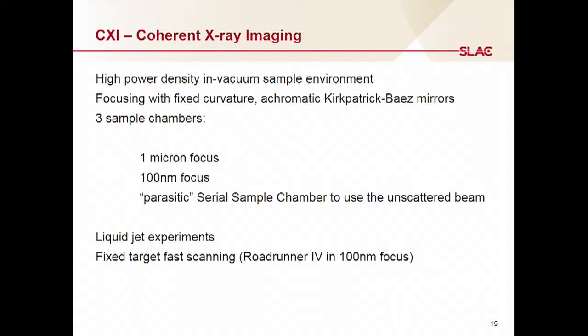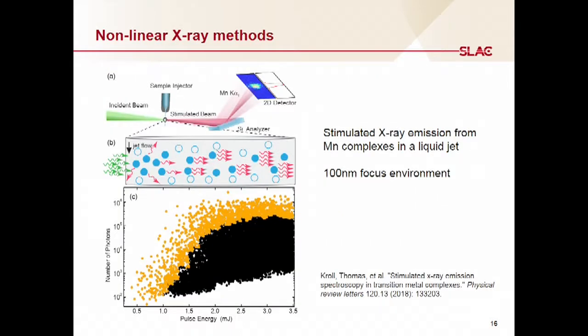There's, in addition, a parasitic serial sample chamber, which is after the 1 micron focus, so that the undiffracted beam can be used to do a parasitic experiment afterwards. This also increases the amount of beam time that we can offer. And the main types of experiments that are done at CXI are liquid jet experiments and fixed target fast scanning. This is a new hardware setup, Roadrunner 4, which can be used in the 100 nanometer focus to do 120 hertz fixed target scanning. So one of the very special things I talk about is the high power density. And because of that, you can do a lot of experiments such as nonlinear X-ray experiments.